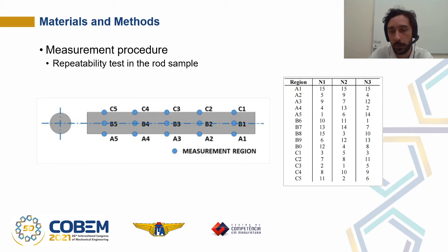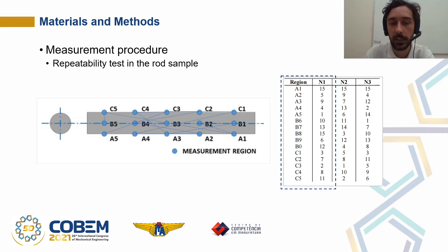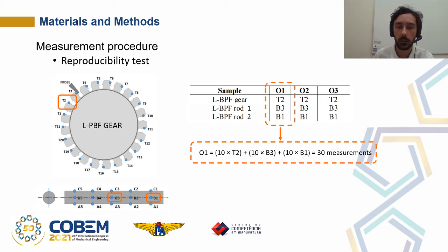Repeatability tests were also performed on the rod samples. The procedure followed the same logic for the 2 rod samples. Each operator had to measure the specific region 3 times in 3 series of repetitions, N1, N2, and N3. The reproducibility test was developed to compare the variation of results between 3 operators.